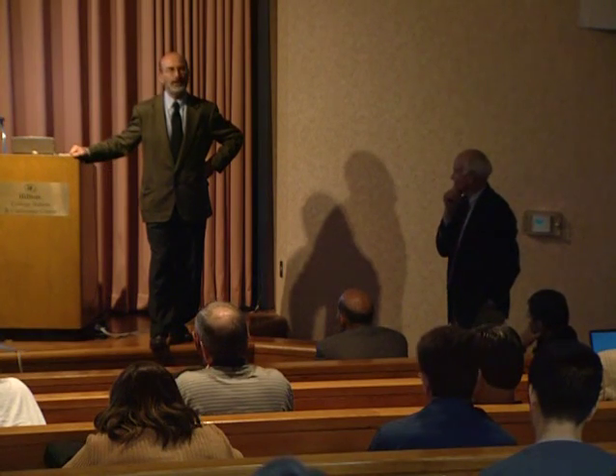Well, you know there are two schools of thought typically associated with compaction. I certainly belong to one of them, which is to compact at the optimum, or if you can, wet of optimum. Because my experience with fills compacted dry of optimum, even if you apply energies of the Proctor energy, normal Proctor, or even a little bit higher, is a bad experience. You get collapse deformations, you get cracking, so it's better during construction operations to live with a relatively high water content, not a good situation, but try to compact at the optimum or wet of optimum, and then you will avoid those complicated problems later: cracking, sudden deformation because of rain or water impoundment. Certainly, this is my feeling.